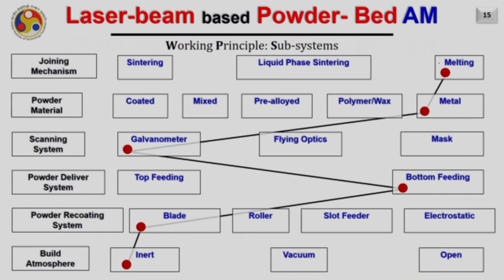Another variant of the system is when the joining is happening by the melting of the powder. The powder material is metal. A galvanometer is used for scanning the top layer of the powder bed, and bottom feeding is used for feeding the powder material to deposit onto the bed. Then a blade is used and an inert environment is used. So here the difference is, in the last case we were using top feeding, here bottom feeding is used. And this particular system what you are seeing right now on this screen is more popular in all the existing machines. If you talk about the machine by EOS, the machine by Renishaw, the machine by DMG, all are used to having the bottom feeding mechanism and available options of the subsystem like I have shown here.